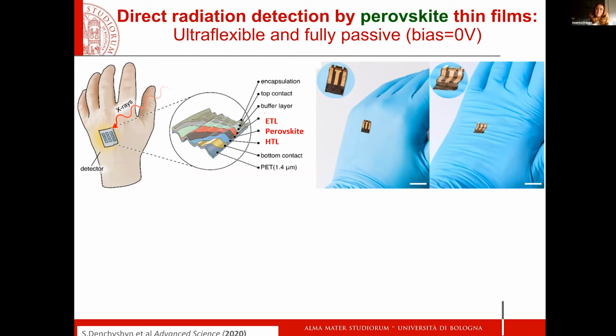So we decided to basically rely on all this knowledge, and we slightly modified solar cell structures that were already fabricated to be, as you can see in the image, ultra flexible and ultra thin. So here, what I'm showing you is a device which has the same perovskite, which is an organic CsFAMA perovskite. I'm sorry, I haven't reported the formula. And we have played around with the other layers, with the other heterostructure layers.